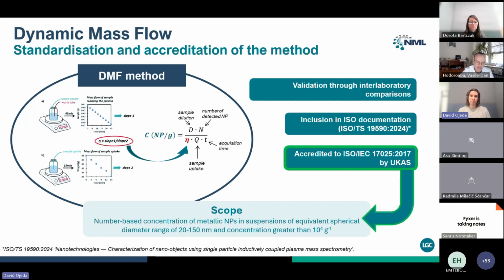Apart from this validation through interlaboratory comparisons, the DMF methodology also went through a process of inclusion within the ISO documentation for the characterization of nano-objects using single particle ICP-MS. And really recently, the method has also been accredited by UKAS, with a scope specifically for number-based concentration of metallic nanoparticles in suspension, of equivalent spherical sizes ranging from 20 to 150 nanometers and concentration greater than 10 to the fourth particles per gram.